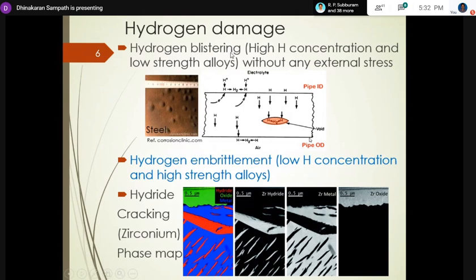In the case of hydrogen embrittlement and hydrogen blistering, we don't need any external stress to effect this failure. And in hydride cracking, as I told you in zirconium alloy, here we are seeing a phase map. The phase map shows, for example, that this material has zirconium hydride, zirconium oxide, and pure zirconium. The blue is all zirconium, and the red is all zirconium hydride. The red regions are very brittle compared to the blue, and the green one is the oxide, which is at the outer surface.